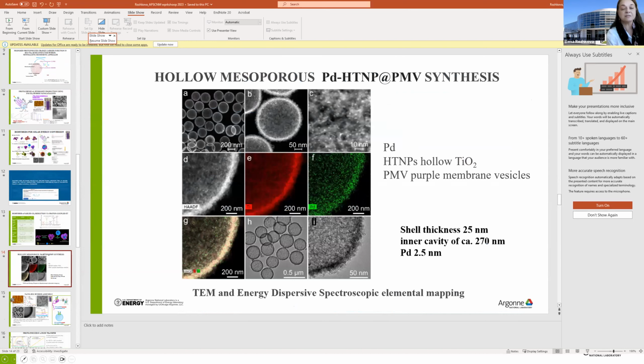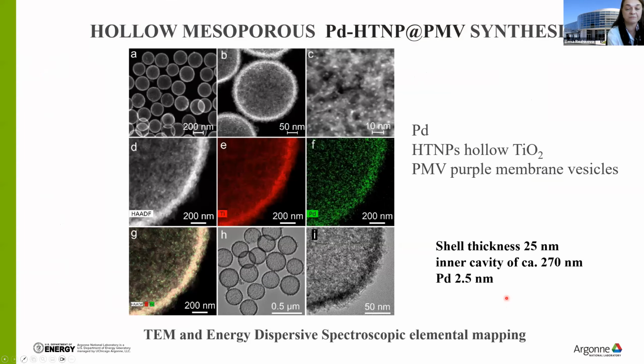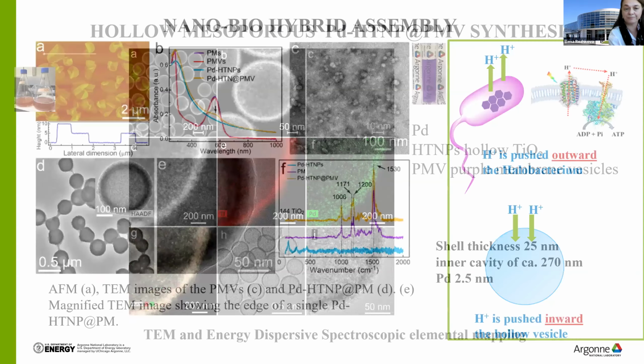So based on this TEM and EDS data, we can see all mentioned elements present, and shell thickness is around 25 nanometers, while the inner cavity is 270 nanometers, and the size of palladium co-catalyst dots is around 2 to 2.5 nanometers.